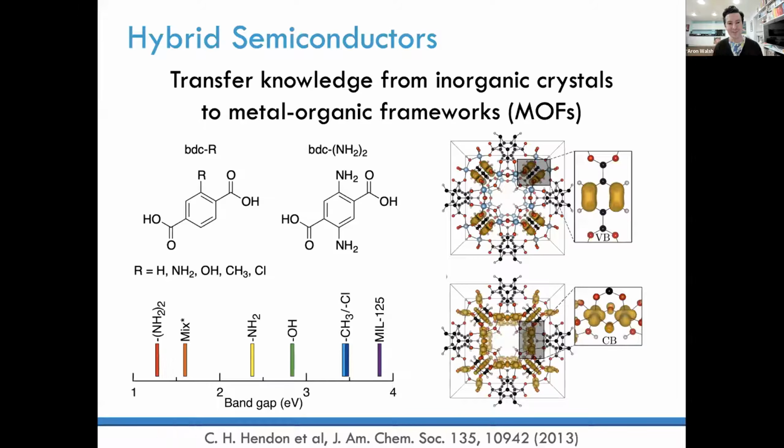But what I would say, back then, 10 years ago, it was incredibly difficult to set up calculations for metal organic frameworks. Often the structures you get from experiment are quite incomplete, usually missing hydrogen. And quite often you have partial occupancies because of how they refine the structures, where you have some orientational flexibility in ligands. So then they end up fitting a 50% site here, 50% site here. So there was a lot of manual effort to actually parse the experimental CIFs into something that you could run a DFT calculation on.